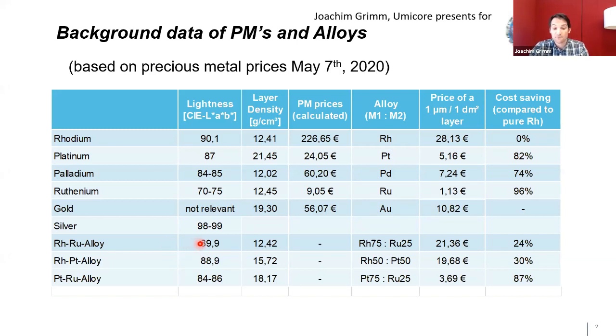You can do the same with plating. Even if you have a little bit higher density, 12.42, forget about this small number. It's more or less the same density as pure rhodium. And in this mixture, it's 75 to 25% ruthenium inside. The lightness, so the white color, will still be at 89.9 compared to 87. So it's still much whiter than pure platinum, for example.